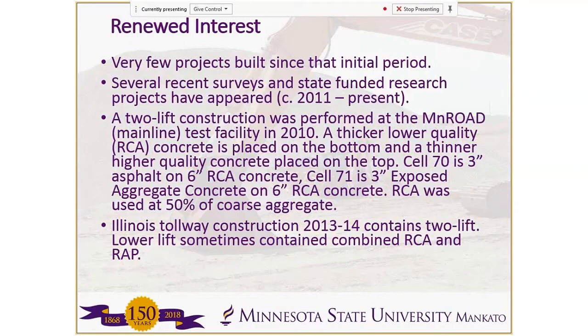One of the more recent constructions was at MnDOT, actually, a two-lift construction, which was performed at the MnROAD facility in 2010. With the two-lift approach, the idea is that you can use a lower quality concrete on the lower lift and then use a higher quality concrete on the top lift. So a thicker, lower quality concrete with recycled concrete aggregates was placed on the bottom, and a thinner layer was placed on the top. Also in the Illinois Tollway construction in 2013, that was also a two-lift construction, and in some portions the lower lift also contains recycled concrete as well as recycled asphalt.